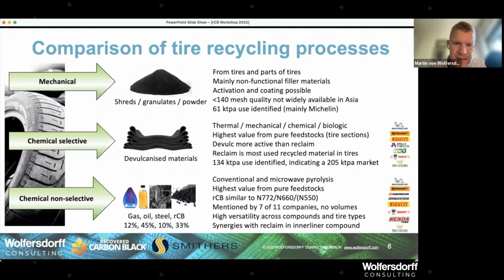Now, the interesting thing is that of these 11 companies of this study I did, 7 mentioned recovered carbon black is a strategic material because they can put recovered carbon black across several compounds and tire types, so it has a high versatility. However, the available volume nowadays, that study was done last year, but even this year, the available volume hasn't grown. We'll see. I think, and a colleague of mine at Wolfersdorff Consulting, Paul Eiter, we think the volumes will grow. There will be major growth in a couple of years, but still, it's not a material that is industrially available.